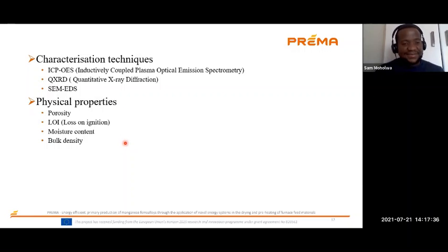Then the as-received samples were tested for their physical properties. We did a helium pycnometry to determine the porosity of this ore. We also determined the loss on ignition. We also dried these samples overnight to determine the moisture content, and we determined the bulk density. This bulk density was determined per size range.